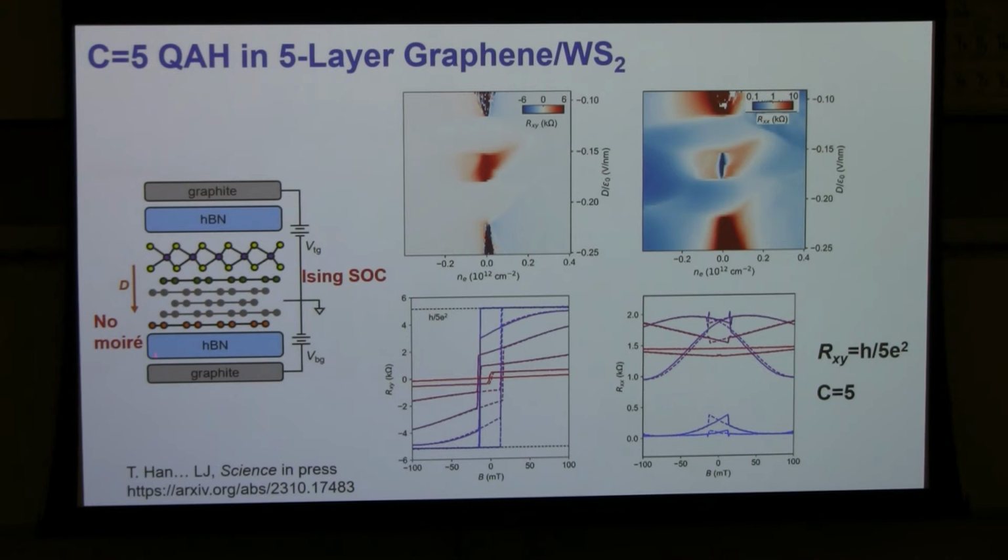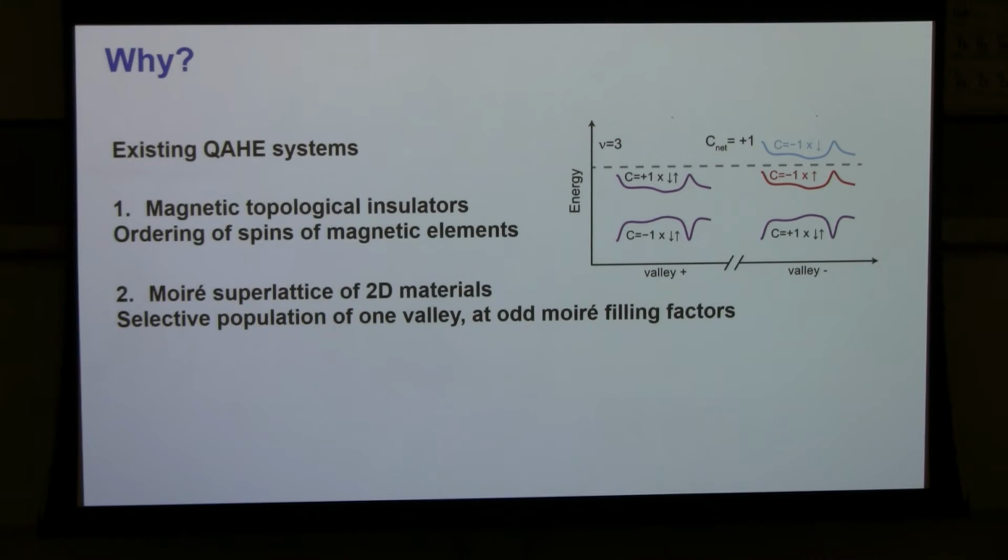If you notice, here I purposely twist away from 0 degree between graphene and HBN, and I minimize the Moiré effect there, and we don't think this has anything to do with Moiré. Phenomenologically, the quantum anomalous Hall you get from Moiré superlattice happened at not 0 charge density, but a density that's enough to fill one of the bands that has Chern number in it.